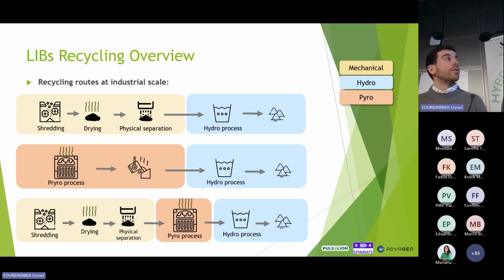So depending on how you combine these pre-processing techniques and the post-treatment, you can have different recycling routes. So I would say these are the main recycling routes at industrial scale right now. The first one is mechanical pre-processing and hydrometallurgical post-treatment. So in the mechanical pre-processing, you start with shredding of the batteries in an inert atmosphere. After this, there is a drying step for the collection of the liquid electrolytes, and then the physical separation of the shredded materials.